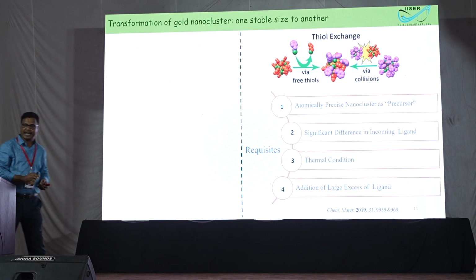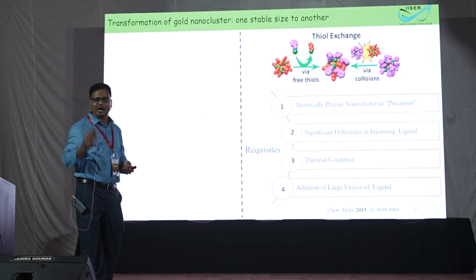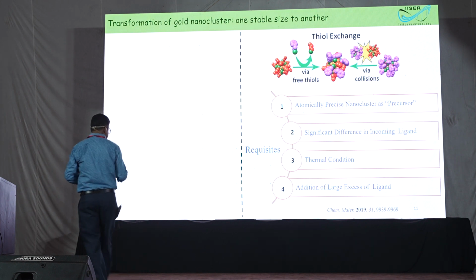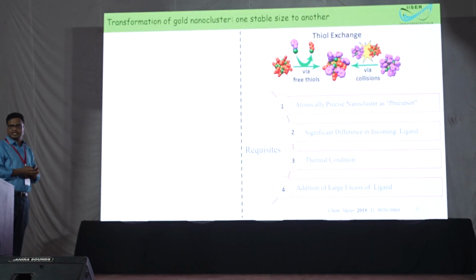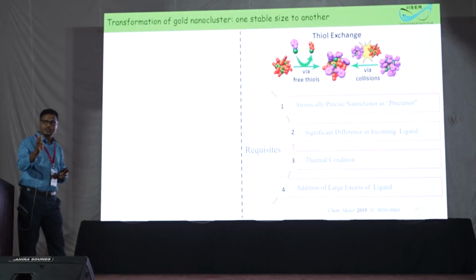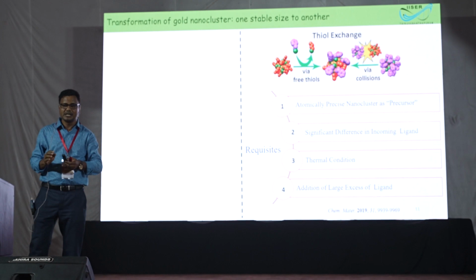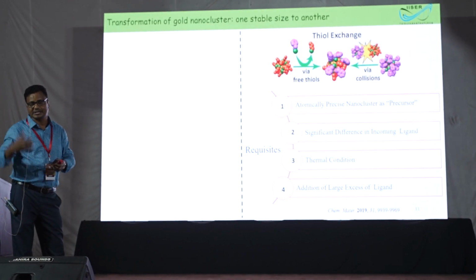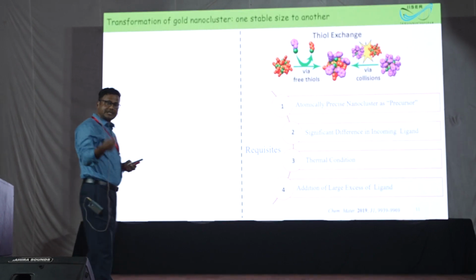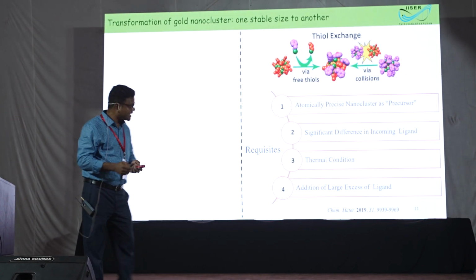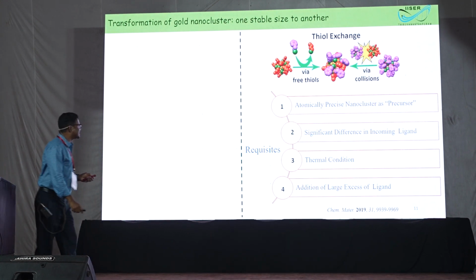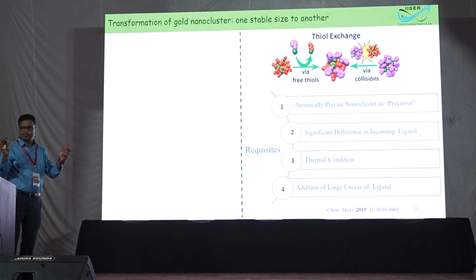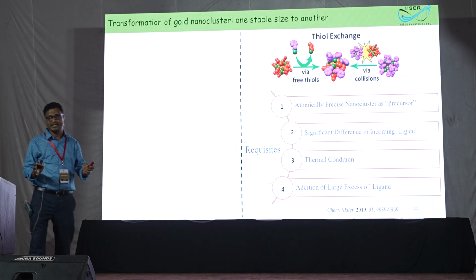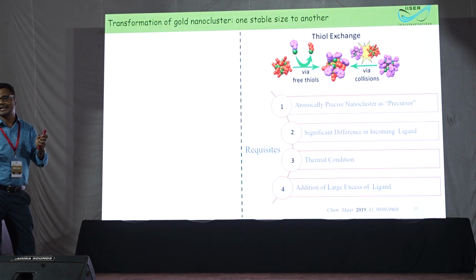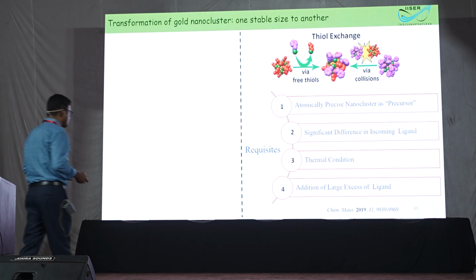My title is on copper and silver, but today I will talk a little bit about gold. The reason I will explain at the end. There are several ways of synthesis, because at the end of the day we need to synthesize them atomically precise. For purification, like in organic chemistry, they run a column, or you can use crystallization; sometimes you get it, sometimes you may not. There is another technique called ligand exchange. If you want to do ligand exchange, these are the parameters to be fulfilled. Your precursor should have well-defined structural information. Your incoming ligand should be different from the existing ligand, and you need to activate the cluster.